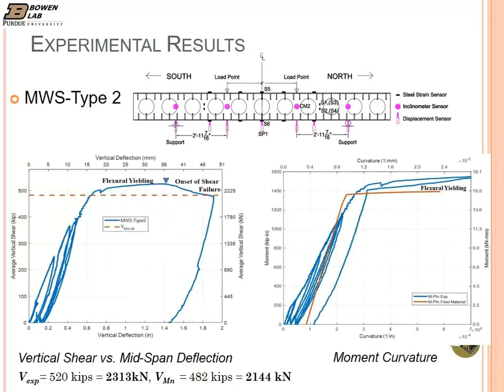And again, we're looking at the moment curvature response. This time, the stiffness is slightly smaller than the 2D section analysis, and that's probably because this time we don't have the inner plates contributing in the interfacial shear. For this specimen, interfacial shear transfer is only relying on the shear studs, which have to develop the plate in this very short distance. Remember, this specimen has yielded in this region, so you have to develop the plate in this very short distance and only relying on the shear studs, because they probably deformed. That's why we see some partial composite action and not full composite action for this specimen.